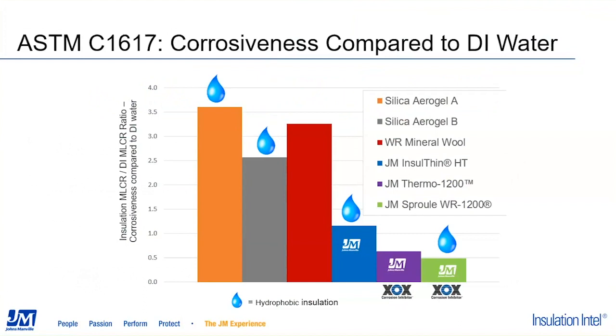This is some data that was developed by a third-party outside laboratory. And what it is representing is the mass loss corrosion rate ratio between the insulation material and the baseline corrosion rate for DI water. DI water, as many of you probably know, is considered to be pretty inert and not have a high level of any type of contaminants in it. So using that as a baseline gives you a good comparison for looking at the corrosion rate as a result of introducing anything that may have leached out of the insulation.